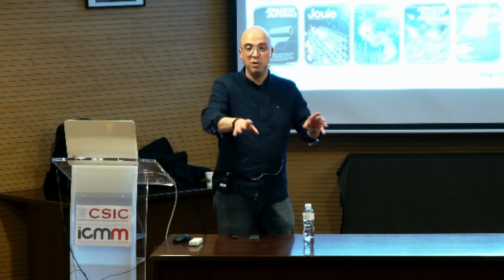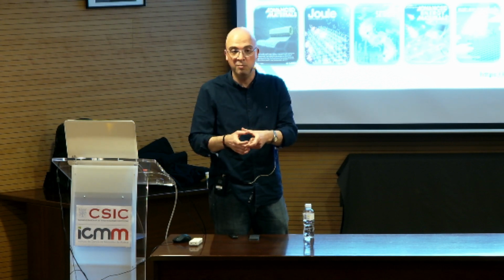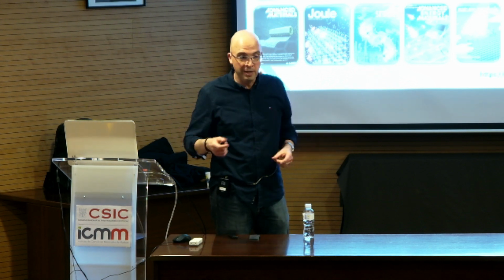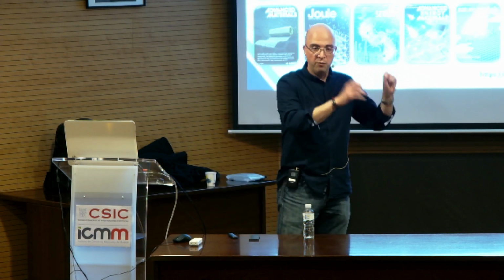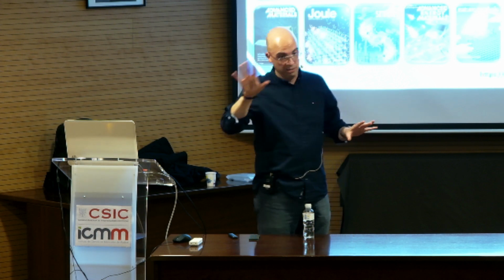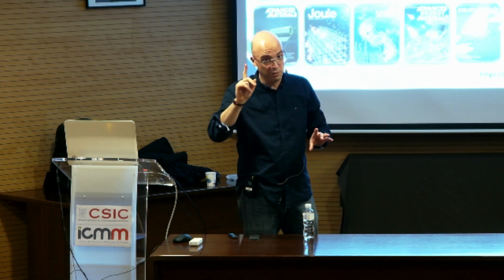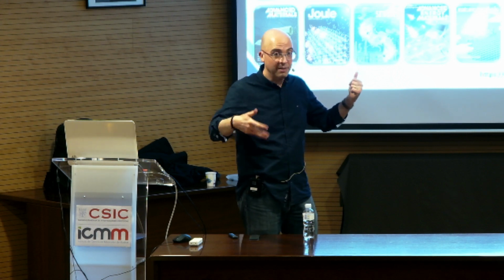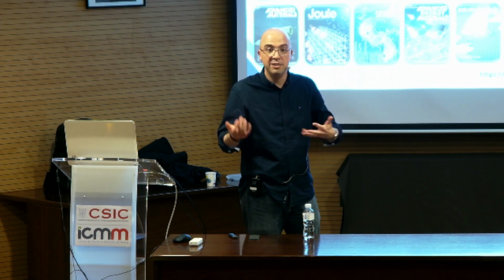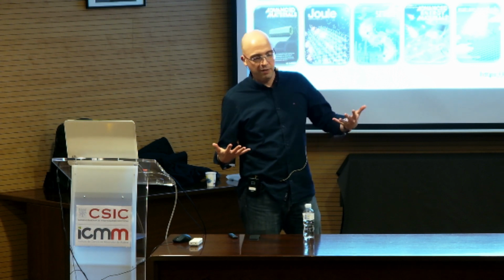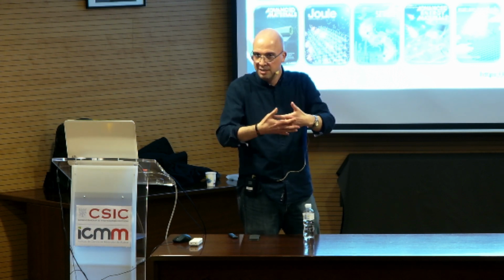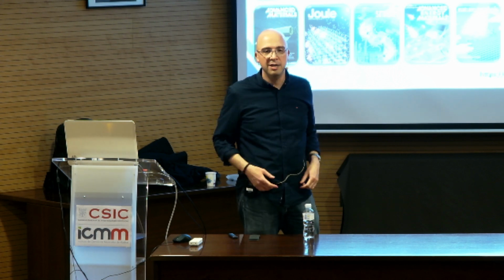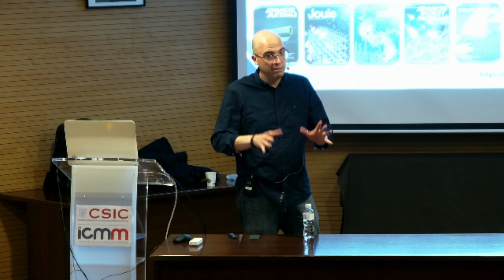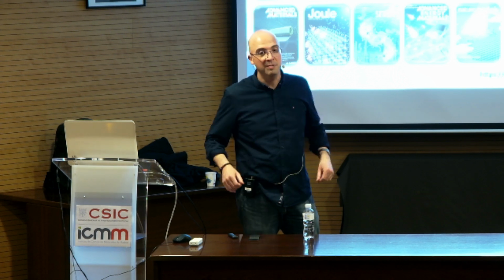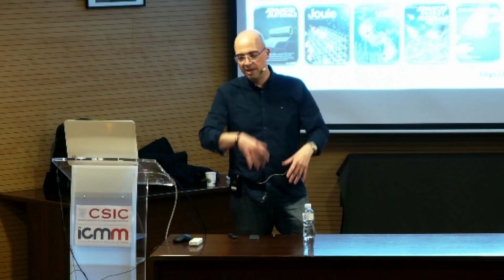We were lucky because there were grain boundaries everywhere. The size of the grains was 5 to 10 nanometers, so in one picture, we took many of them. But the idea is going to another site, focusing, getting the corrections, etc., and then moving to the place where you want to take the picture and getting the first one. Because in the videos, if you are there for several seconds, what you see is that there is a reconstruction. You are not really merging the grains, but you really are changing completely the type of boundary you have. So the only way is to get the first picture, and that's all. It's steady for a few seconds. After that, everything moves.